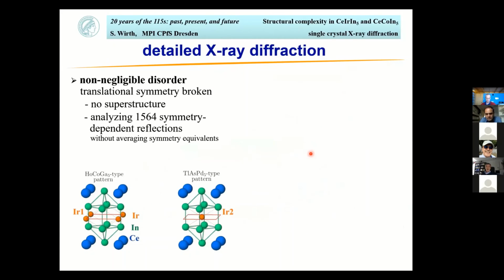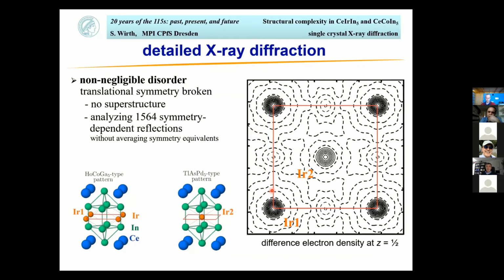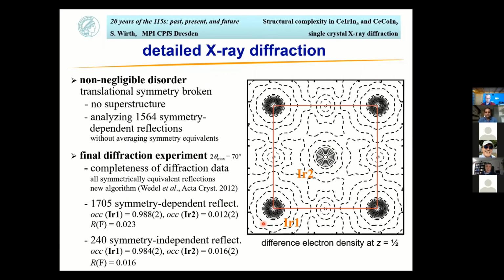So keeping that in mind, if you now do an X-ray diffraction experiment, you need to consider that there is no translational symmetry anymore. So we don't have any superstructure. You have to basically analyze all the symmetry-dependent reflections. And that was done. And what you get here is actually this difference electron density, calculated from these diffraction patterns, but only by considering the cerium and the indium atoms here. So what's basically left is the iridium. And then you see very nicely the iridium here at the regular pattern. This is what we call here iridium 1 at the corner. But then there also seems to be some iridium here at the center, corresponding to this structural pattern here. So if we keep that in mind, our X-ray experts actually designed a real new algorithm to actually look at the completeness of the diffraction data.